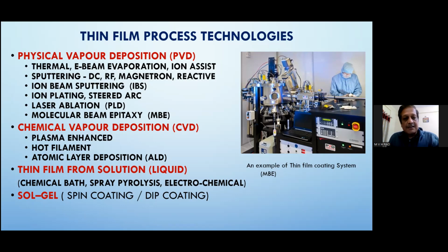Spray pyrolysis is somewhat like CVD. It is basically a CVD process only in this case. The only difference is, instead of introducing a gas, the spray is a solution. The solution is atomized and sprayed onto the hot substrate. By the time the solution hits the substrate, it is in a very misty form, like a mist. Once it comes into contact with the surface, the solution atoms and molecules decompose and then the reaction takes place. So that is also one nice technique. Essentially this is from solution to thin film, but intermediately, just before the solid is formed, it turns into a vapor and then the reaction takes place and the solid is formed.